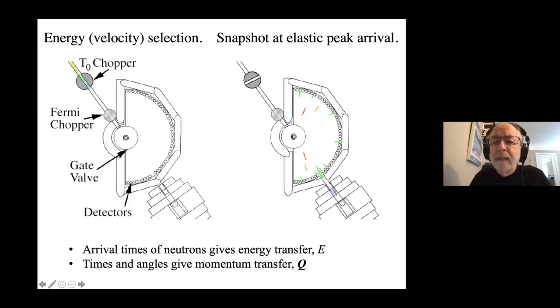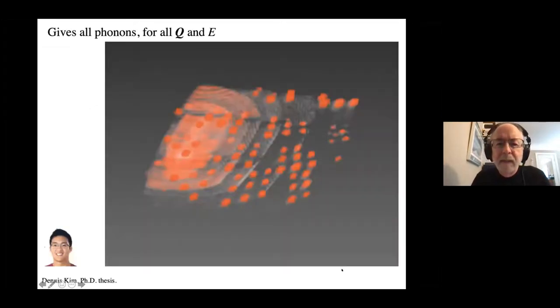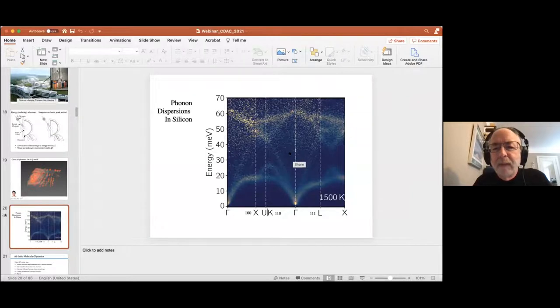Now, recently we've been using single crystals. And in this case, we take the single crystal, we rotate it by about 200 little steps, maybe over 90 degrees in angle to collect 200 different data sets here, which we can put together and reassemble the inelastic scattering as a function of vector Q, which spans over the whole Brillouin zone of the crystal, actually. So we get a lot of detailed information. Dennis Kim made a little movie of this for his PhD thesis. This is a silicon crystal, and this is a sum of the phonon dispersions for silicon.